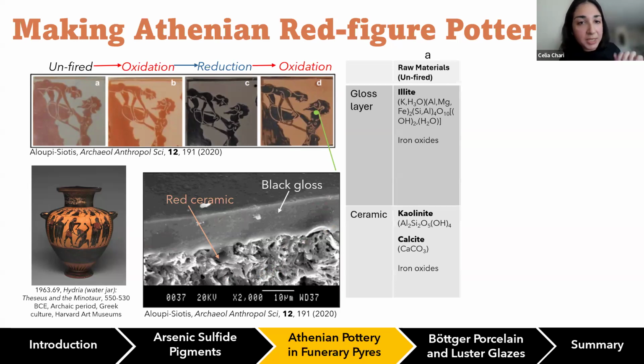You start off with raw materials, and the composition of the raw materials of the gloss layer is very different to that of the ceramic substrate. The gloss layer contains large amounts of illite, so this is a potassium-rich aluminosilicate, and also iron oxides, while the ceramic contains other types of aluminosilicates, like kaolinite, and high amounts of calcite, as well as iron oxides.